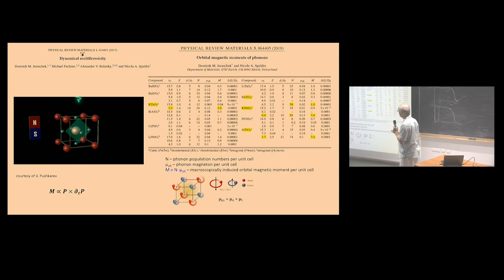But let's go to dynamic multiferroicity. I have only 7 minutes, so quickly. Dominik Juraschek from Nicola Spaldin's group proposed that if you have, let's say, a perovskite, and you excite phonons using a circularly polarized beam, then the atoms start to move circularly. This circular motion of charge produces current, and this current produces a magnetic moment. Juraschek calculated the magnetic moment in different compounds. Here is the list of perovskites, and the strongest effect is expected in strontium titanate and potassium tantalate.